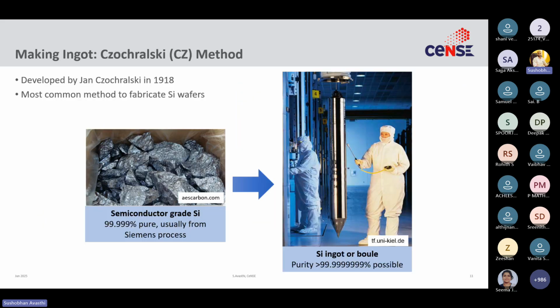So the polysilicon basically looks like this. It's basically chunks of silicon that have been ultra purified. By this time, after the Siemens process, this material is already 99.999% pure. There is no further metallurgical process by which we can refine it any further. The way we refine it further is we actually make wafers out of it using a method called the Czochralski method. It's a crystal growth method.